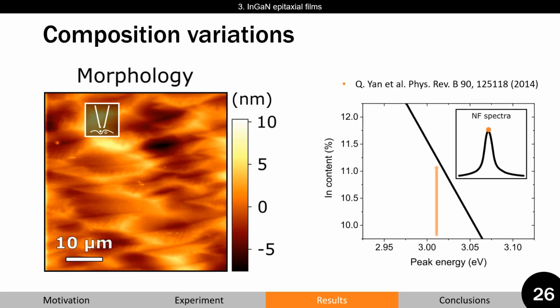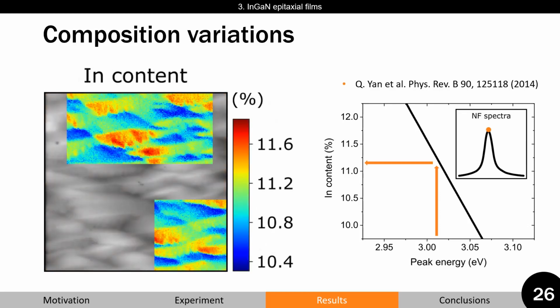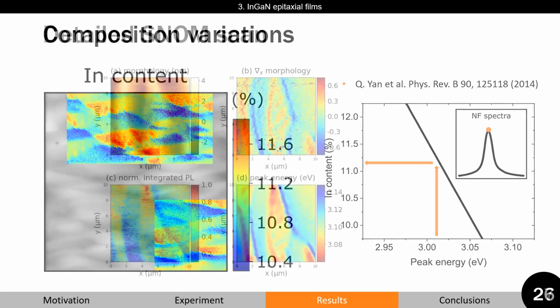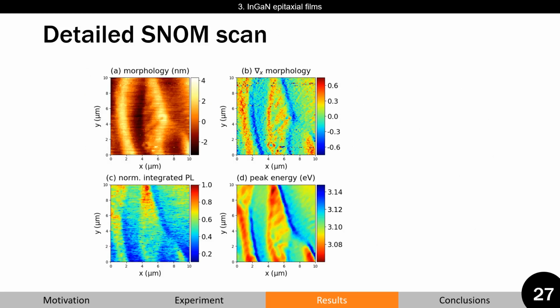We took the peak energy position of our near-field spectra and converted it into indium content. By superposing our indium content maps, we see that there are large indium composition fluctuations, which visually seem to correlate with these undulations. Therefore, we decided to do more detailed SNOM scans. Here is an example, 10 by 10 micrometers.